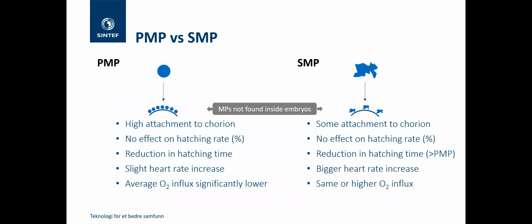When we looked at the primary versus the secondary particles, for the primary, we didn't find any particles inside the embryos. That's something we checked and we didn't expect to. So this must be a surface related issue. What we saw with the primary was a high attachment to the chorion, the outside surface. There was no effect on hatching rate. There was a reduction in hatching time, and a slight increase in heart rate. The average oxygen influx was also significantly lower for the primary particles.